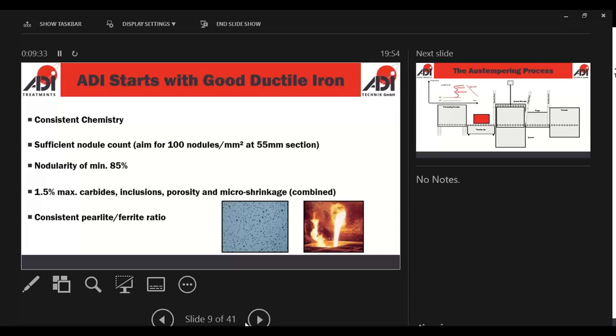Carbides and shrinkage, obviously we want to minimize that as you do in a standard casting. We also want to do so when we're producing good ADI. And the final one there, consistent matrix, is there mainly for components that are pre-machined. We're producing a tough material, and machinists don't like machining tough materials. They like machining simple materials, normally ferritic grades of ductile iron. They're sometimes not even happy to machine pearlitic grades of ductile iron. Obviously, ADI can be tougher to machine. It is machinable, but if we can machine it before, it obviously makes a lot of life easier. And by giving a consistent structure, we can do that.